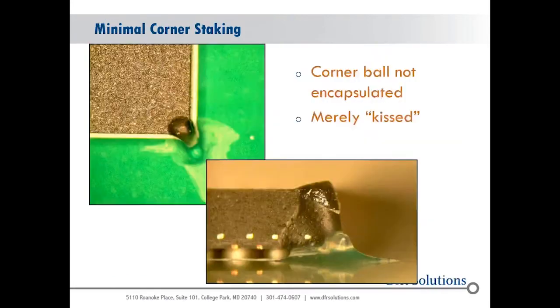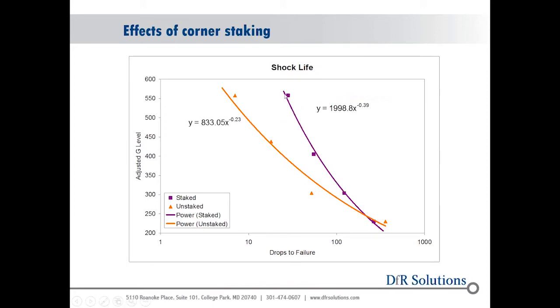Just some different loading conditions. This is just another example of adding a little bit of staking on the corner just to sort of glue that part down, and will that have an effect? And yes, just a little bit of staking. This just shows you how sensitive shock can be to just a small mechanical change to the system. So the staked joints lasted quite a bit longer. At least time to first failure was about 2x higher. Once you start getting out here, it doesn't really matter. We're starting to get into low cycle fatigue type of action here above 100 cycles. But definitely time to first failure. And really, is somebody going to drop it more than 10 times? Hopefully not. But adding a little bit of staking will get you a little bit of margin.